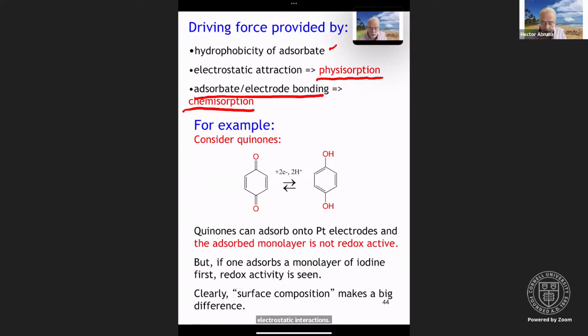Case in point, quinones, which are one of the best known, oldest, and most heavily studied redox active molecules. In the redox transformation, you go from the quinone on the left, a 2-proton, 2-electron system, to give you the catechol or the hydroquinone on the right. So you exchange 2 electrons and 2 protons, proton-coupled electron transfer. Quinones can adsorb onto platinum electrodes, and the adsorbed monolayer is not redox active. Let me repeat that. Quinones can adsorb to platinum, and they are not redox active.